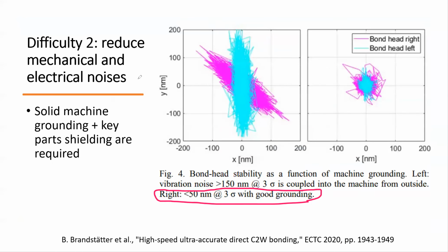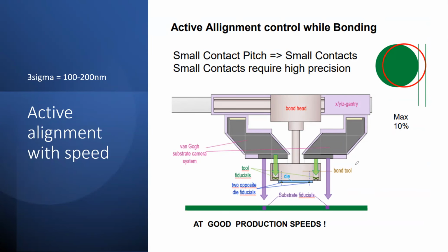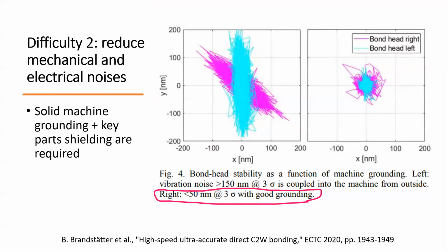And then the second is you need to reduce the mechanical and electrical noise. Imagine you are running a lot of mechanical motion here, right? A lot of mechanical things are moving in and out. They are all driven by certain motors. A motor can generate an electromagnetic field, and that will generate noise, right? Magnetic field eventually can induce eddy current and can do a lot of crazy stuff to make your fine control not so fine. So to achieve such a fine control at 100 nanometer scale, you have to do a lot of grounding, right? A lot of good grounding and then the shielding. So your machine has to be redesigned pretty much, at least enforced by certain new grounding. Grounding is super important, right? It is one of the biggest challenges.